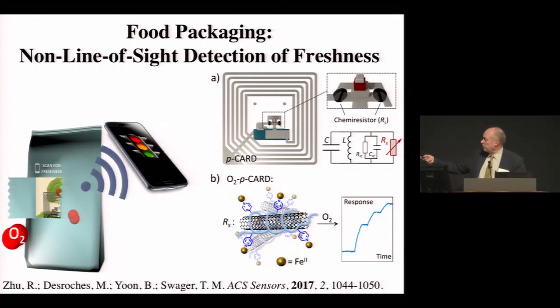And so the way we've done that is we actually have this platform where we have another polymer that goes around the nanotubes. It has pyridines on it, and we put iron 2 species, or iron 2 salts, just simple salts in, and bind them around the nanotubes. Now, iron 2 is air sensitive. It tends to oxidize in the air to iron 3. So we do this under inert atmosphere, and the iron 2 is strongly reducing. So the iron 2 donates electrons to the nanotube, and it becomes very insulating because we've killed all the holes in it. There are no holes. And so the nanotubes are now insulating, but if you give it a whiff of air, it now starts coming up and becoming conductive. Okay? So we have an oxygen dosimeter that you can use for food packaging here.